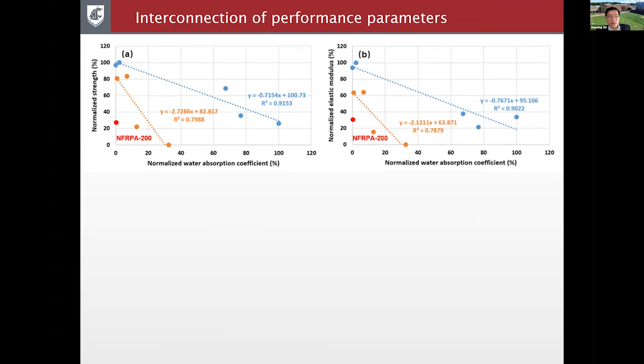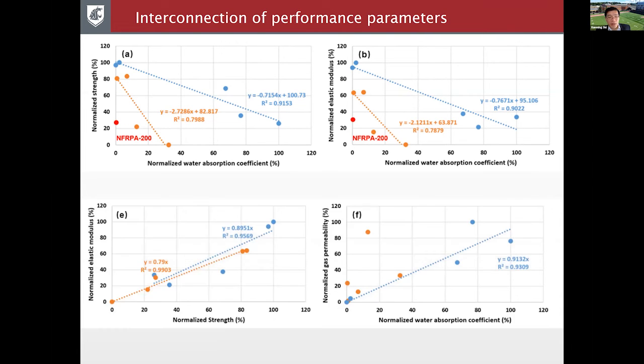Now, also we look at the interrelationship between some of these parameters. As you can see, the pre-aged group, these orange dots, seem to follow a different trend than the new group. But for both of them, the trend is such that the higher the water absorption coefficient, meaning they're more compromised in microstructure, the lower the strength and lower the modulus. In other words, the strength and modulus at the bottom left show that they follow almost a linear one-to-one relationship. So the higher strength, higher modulus, and less compromised microstructure. Same thing on the bottom right, the higher water absorption coefficient corresponded to higher gas permeability and more compromised microstructure.